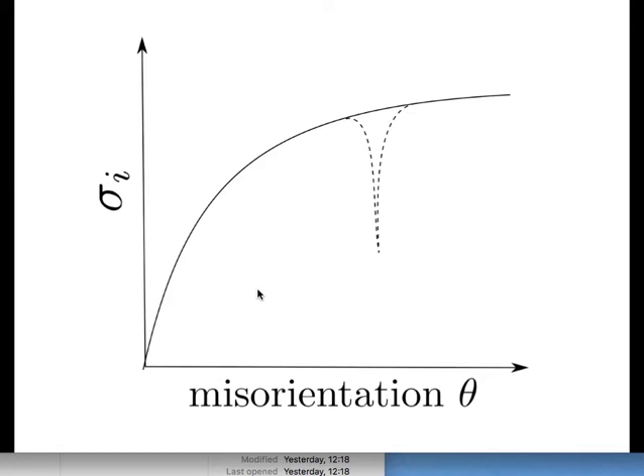Now, I've deliberately drawn this curve as the calculated interfacial energy per unit area, but it turns out that at certain values of theta, the energy sharply decreases. Okay, and I've simplified this. You might find many of these cusps in interface energy at particular values of theta. And what happens is that as I vary the angle theta, at certain orientations you get really good match between the two crystals. And I'm going to illustrate that.